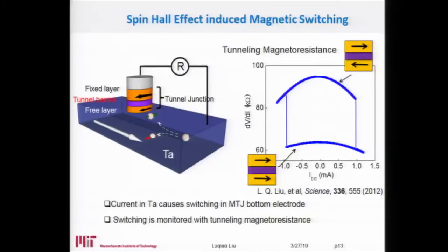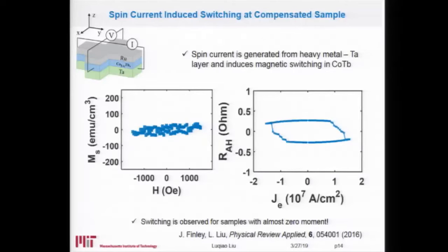So now you have these different resistance states due to the switching from the spin Hall effect of the heavy metal layer. So today we are going to utilize this same effect, but onto the zero moment system. This is a device that we made. The bottom layer is still tantalum, which provides the spin Hall effect or the spin current. And then on top of it, we have this cobalt-terbium alloy, which we try to make zero moment. So we tune the concentration, so the magnetic moment is almost 0.